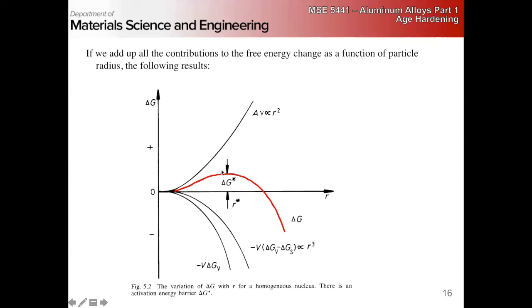Right? If we're at the stable nucleus and it grows, we have a reduction in free energy. So that's naturally going to happen. There's a bias towards jumps that reduce our free energy. If we have a cluster, a nucleus that forms that's less than r star, chances are over time it will go this way to reduce its free energy and go back to the parent phase. Right? So increasing our surface energy increases this activation energy, this delta G star, and increases the critical radius that we need.